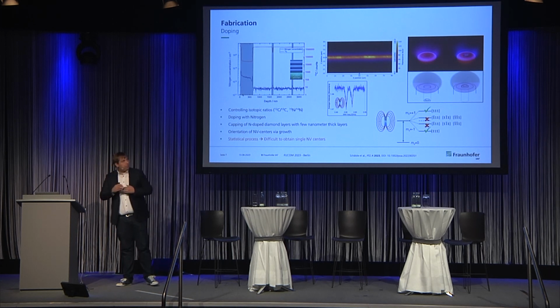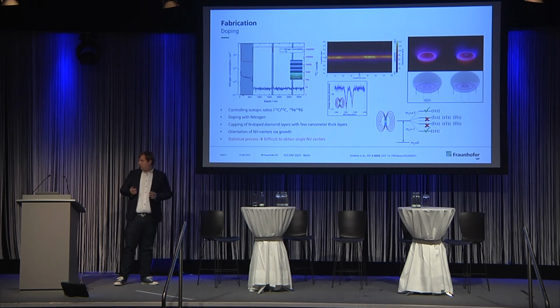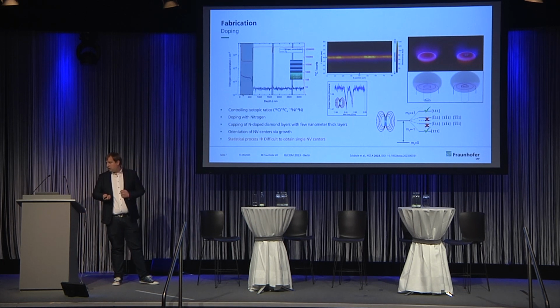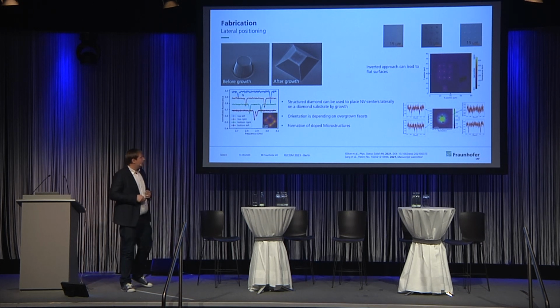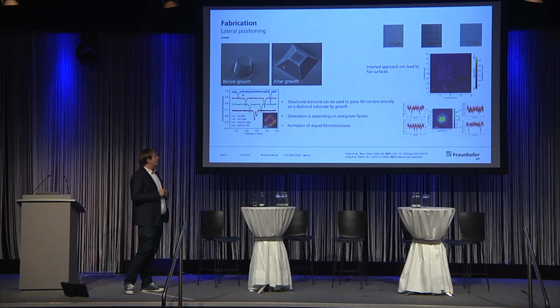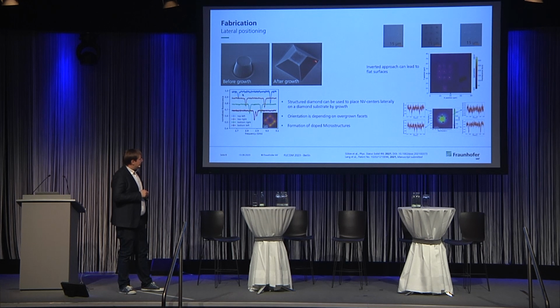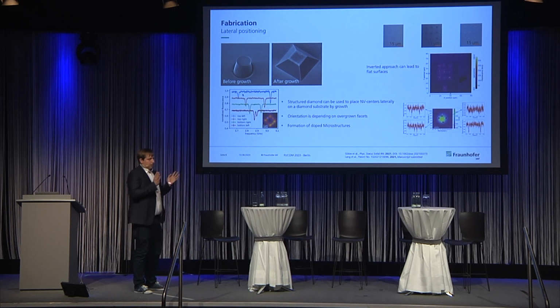So now with very thin films, we can localize the NV center in the diamond, but there's also a possibility to do a lateral placement by growth. You can see here a small microstructure that is overgrown, and using certain parameters, during the overgrowth, you can dope these facets with nitrogen. As these facets are 1-1-1 crystal facets, the NV center will lie orthogonal to these facets, and this can be seen here.